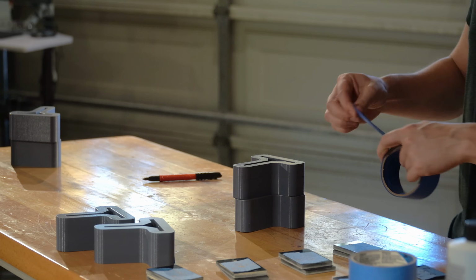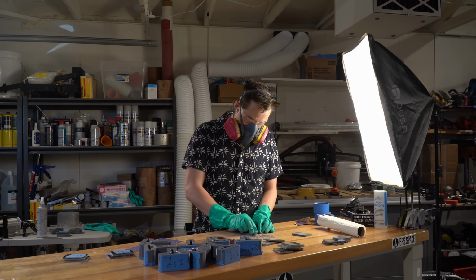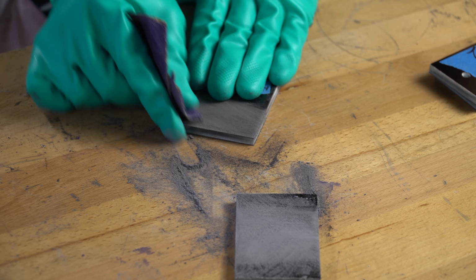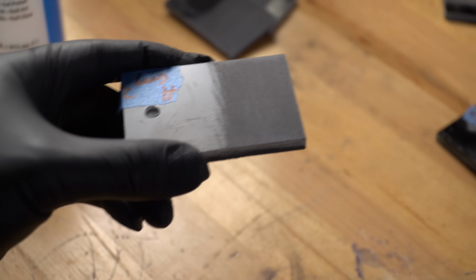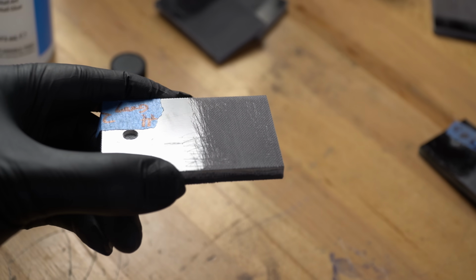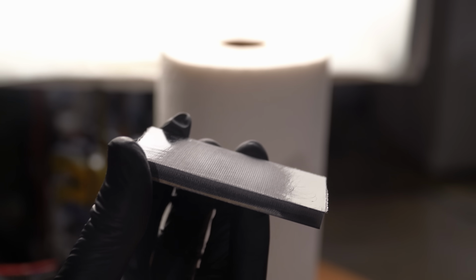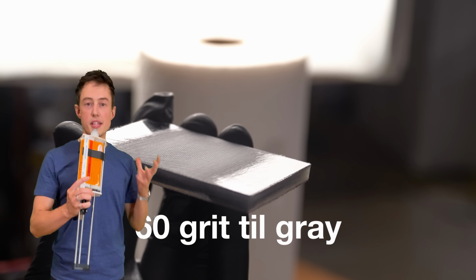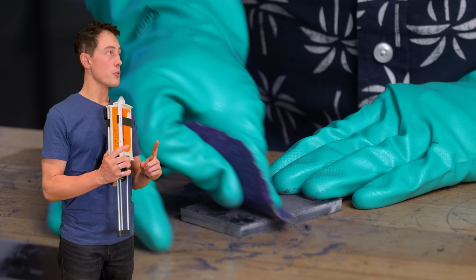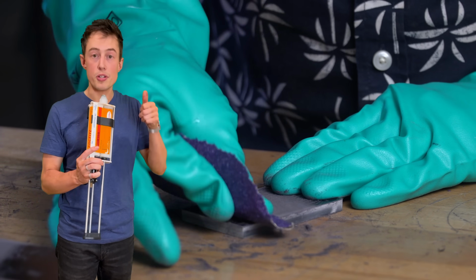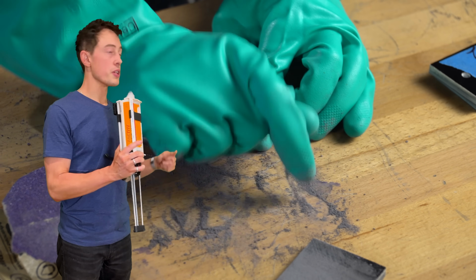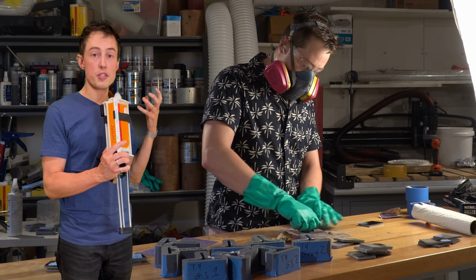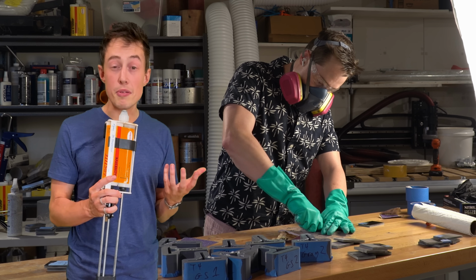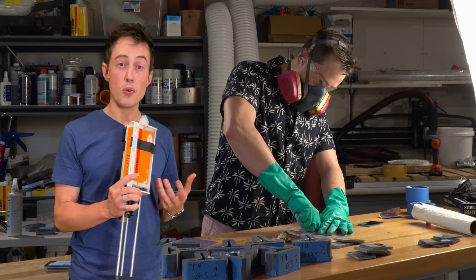On the next round, I prepped 3 sets of dual samples, all with 60 grit sandpaper. The first set were sanded with reasonable pressure until the entire surface went from glossy to matte. This basically ensures the whole surface is fresh, so to speak, and I'm calling these 60 grit till gray. The second set was sanded with 60 grit sandpaper, but much harder this time. I pushed deep into the composite material, hoping to scuff up and expose some of those composite fibers. My thought was that maybe exposing some of those fibers would give us more area to bond with.